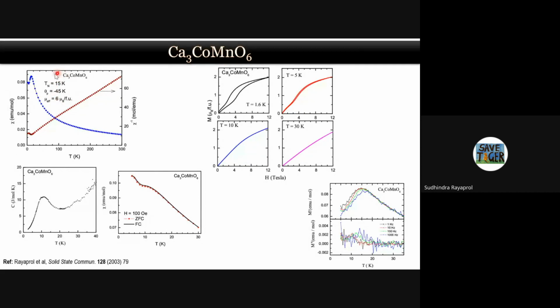But if you look at the valence states, it will come to calcium 2 plus and manganese 4 plus, which makes both of them magnetically ordered. But the interaction is antiferromagnetic, and it is confirmed by the presence of this hump in heat capacity also. It's not a clear lambda anomaly, but you have a hump, which shows that it may not be completely spin glass, but it has a short range magnetic order, which is coupled to the long range magnetic order also. Okay. So if you look at the magnetization, again you have the spin reorientation. So that shows that it has a field induced effect also.